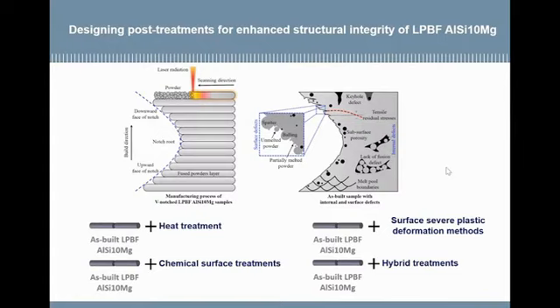So in this study, we have been trying to design different post-treatment methods in order to address and alleviate these adverse effects of surface roughness and high surface irregularity in laser powder bed fusion technology. We selected a notched geometry in order to have this down skin and up skin difference also in terms of surface quality. The post-treatments that we have considered include heat treatment, severe plastic deformation treatment, chemical surface treatment, and also hybrid treatment, so combinations of severe plastic deformation and chemical treatment.